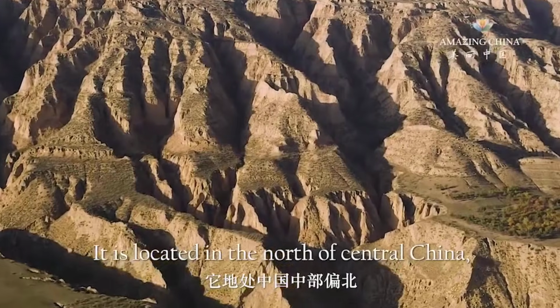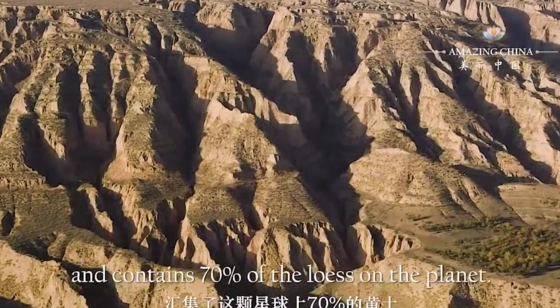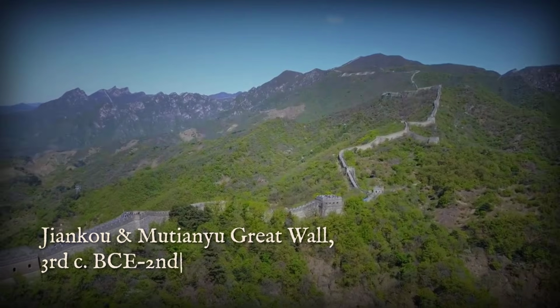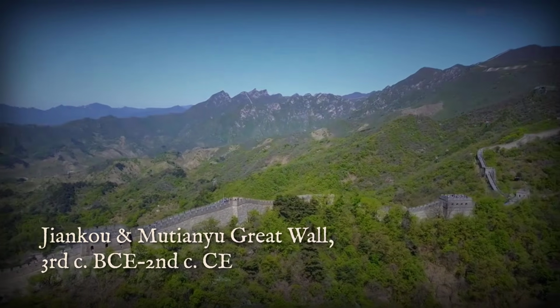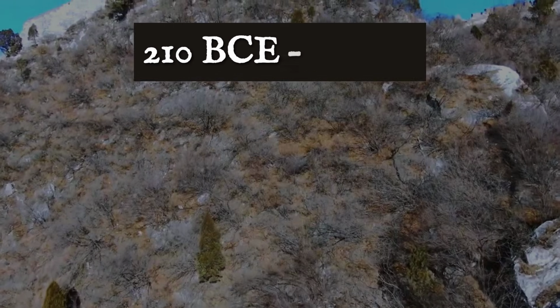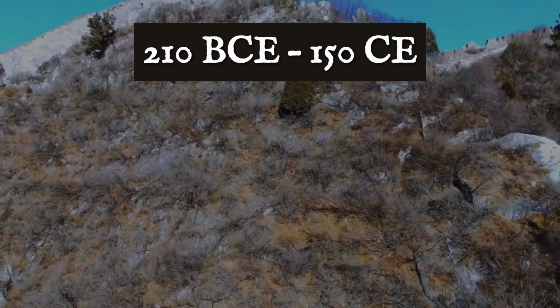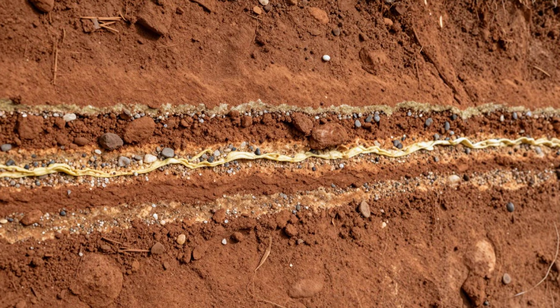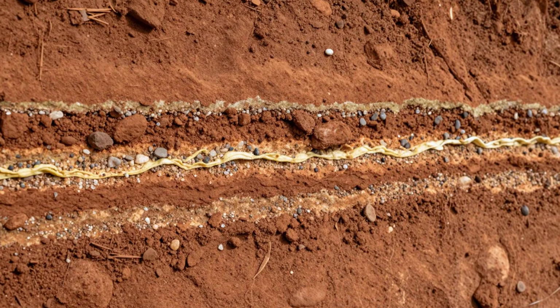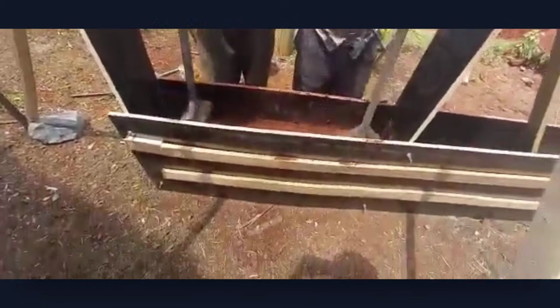Sections of the Great Wall of China, built with rammed earth more than 2,000 years ago, still rise from the Loess Plains. Archaeologists have dated the Jiankou and Mutianyu segments to between 210 BCE and 150 CE. Their cores comprised compacted local soil mixed with lime, layered by hand and tamped to a dense, stone-like hardness. These walls stand not because they were forgotten, but because they were maintained.